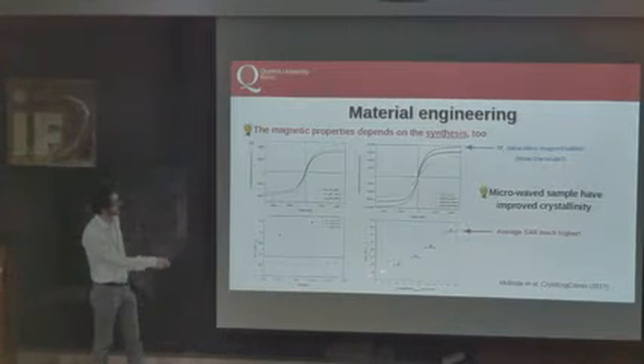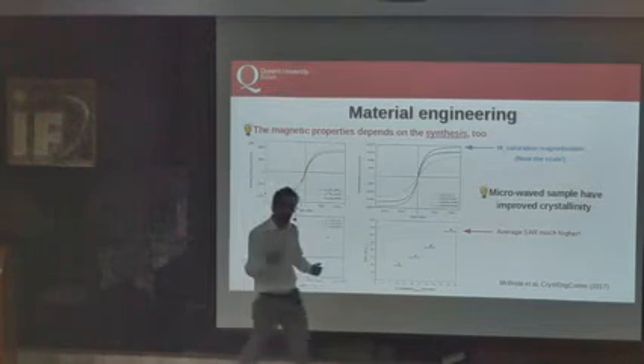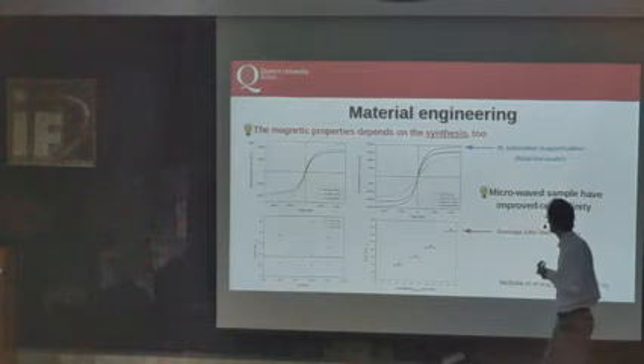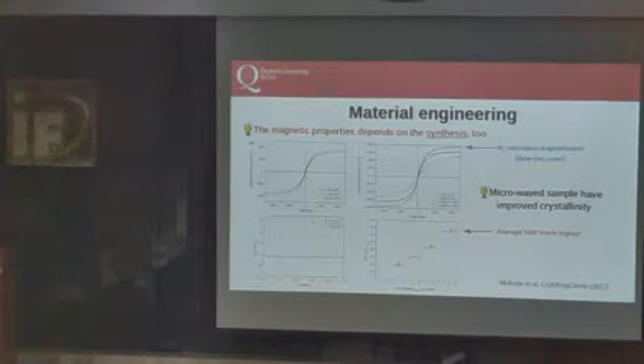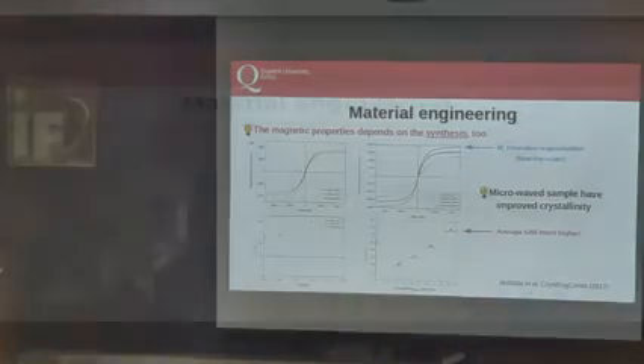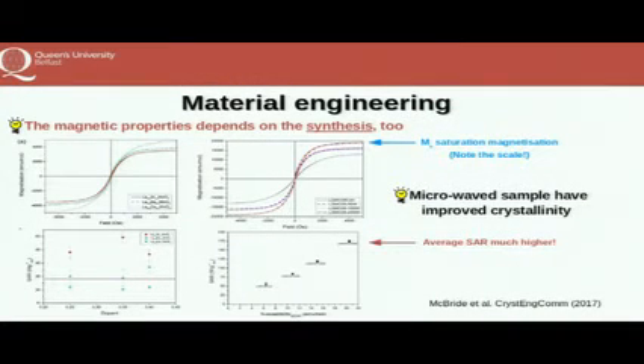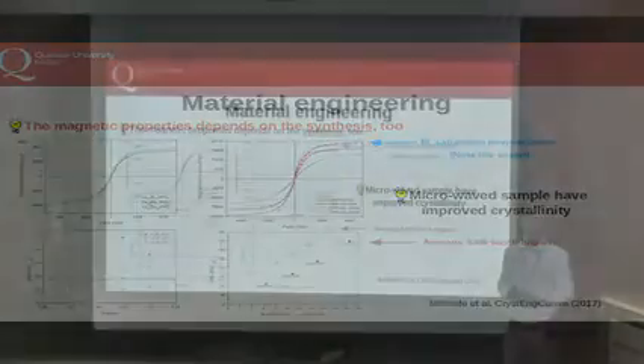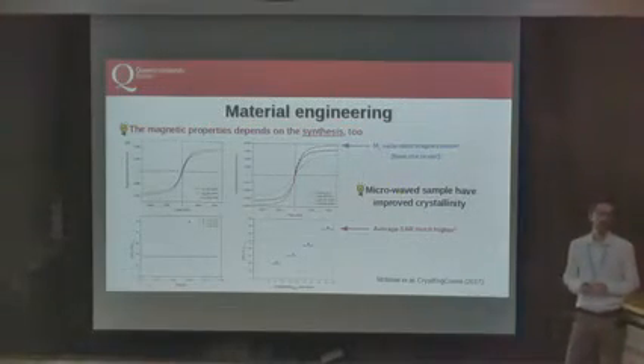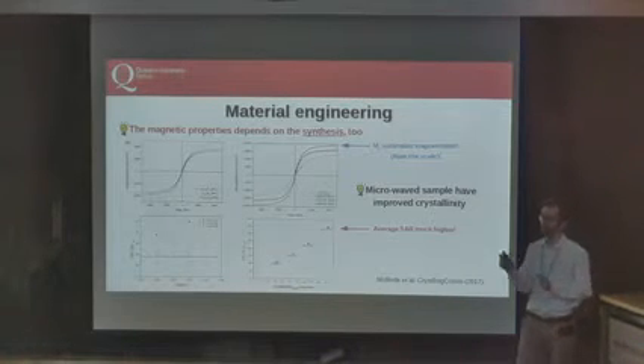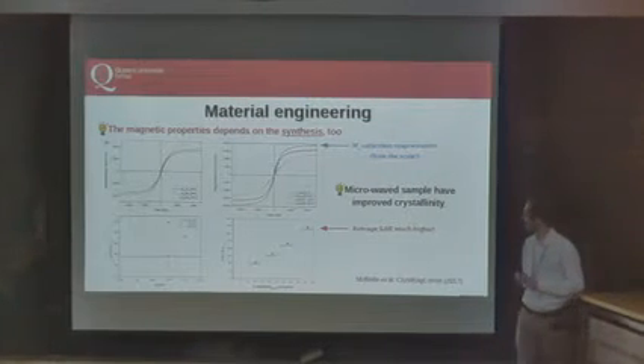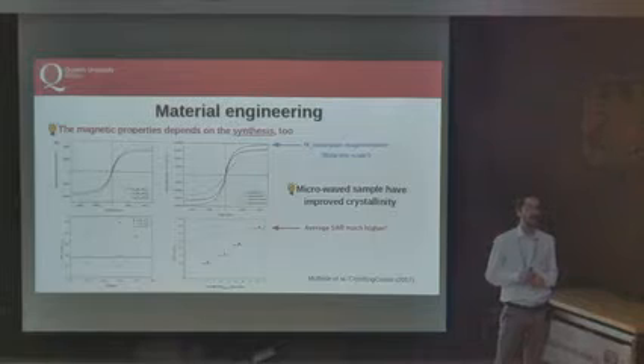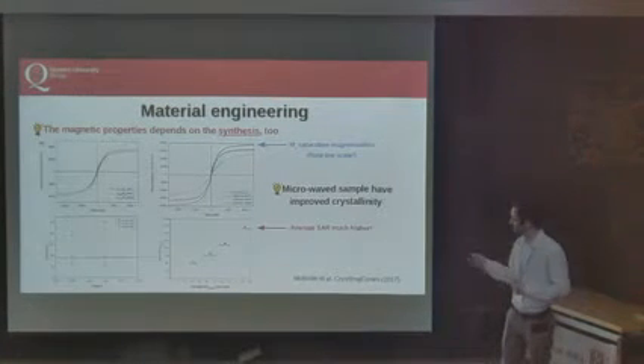And you see that there is a very nice correlation between, let me say, how much time has been exposed to microwaves and both the susceptibility and the SAR. The susceptibility also depends on the crystallinity of the sample. So at the end of this engineering that was done, in fact, in the School of Chemistry and Chemical Engineering, we have very good compounds, relatively close to the theoretical value for magnetizations, still pretty large, 150 nanometers, perhaps a little bit less on average. So we have something that we can start studying also from the numerical point of view.